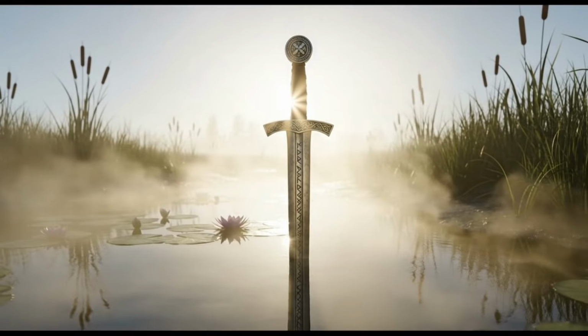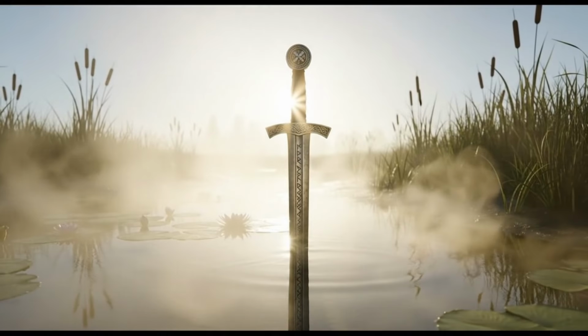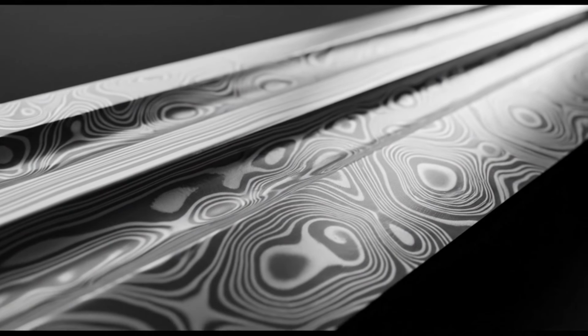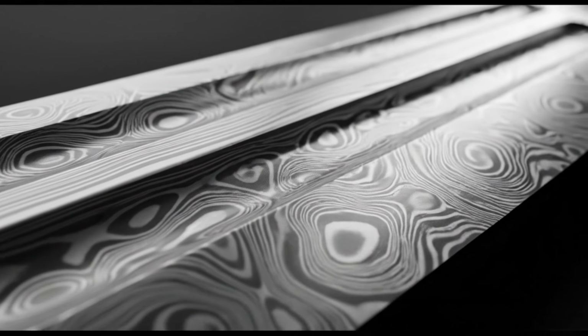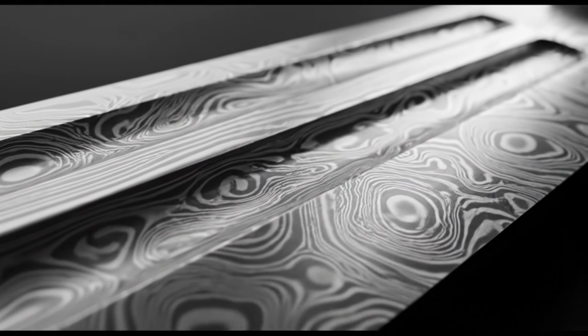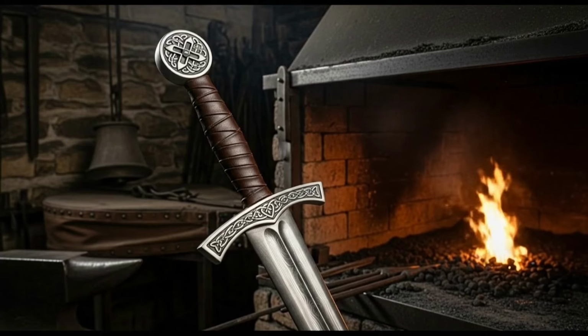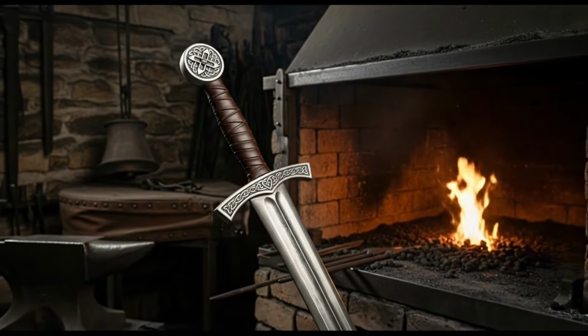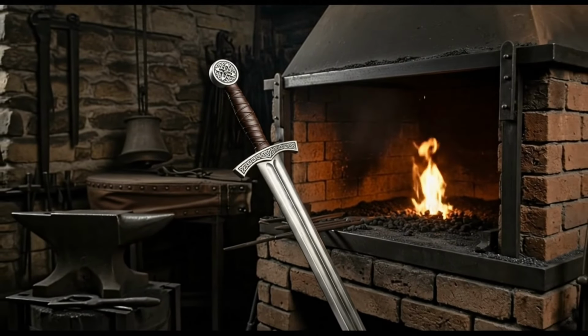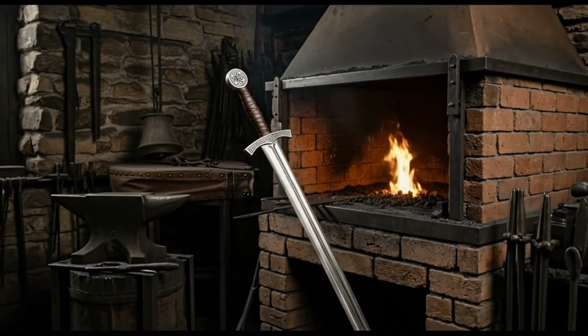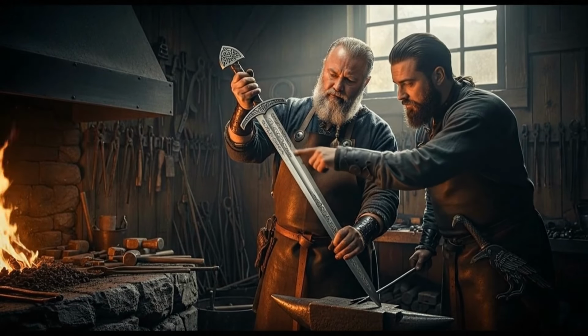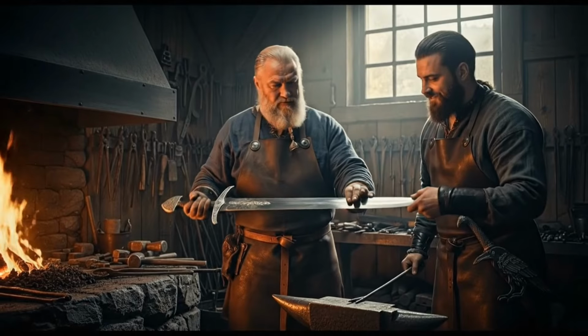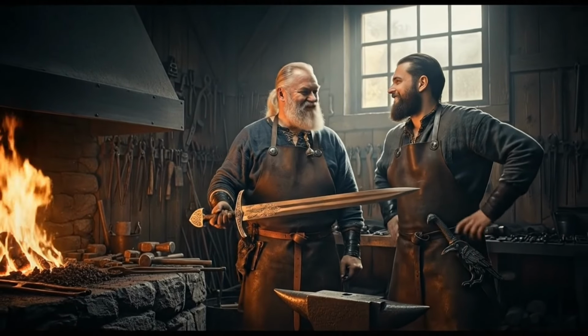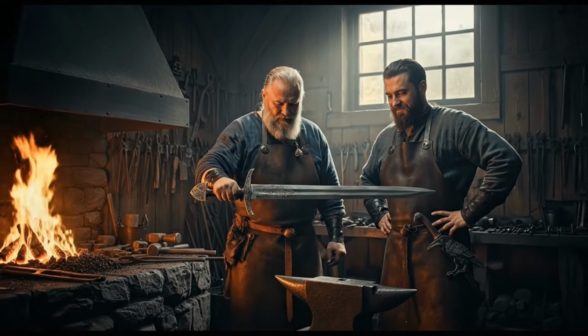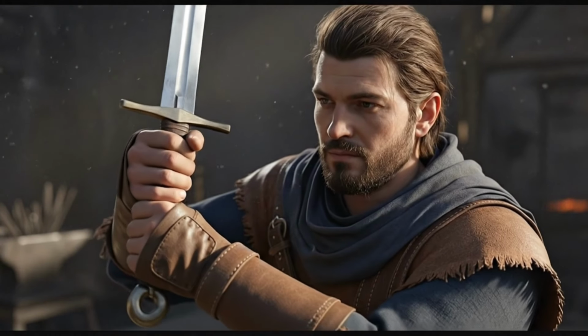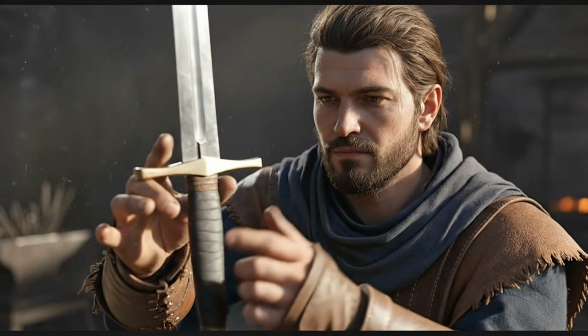Craftsmen used these colors to judge temperature and degree of tempering. Once desired colors were achieved, blades were cooled again. Tempering made steel slightly less hard, but significantly more durable and elastic. It's this balance of hardness and toughness that's the main characteristic of quality metal. Tempering isn't just about heat, it's about finding that perfect balance, that sweet spot where metal is strong yet flexible. Now, blades were ready. They were hard enough to hold edges and elastic enough not to break in battle. All that remained was bringing them to perfection.